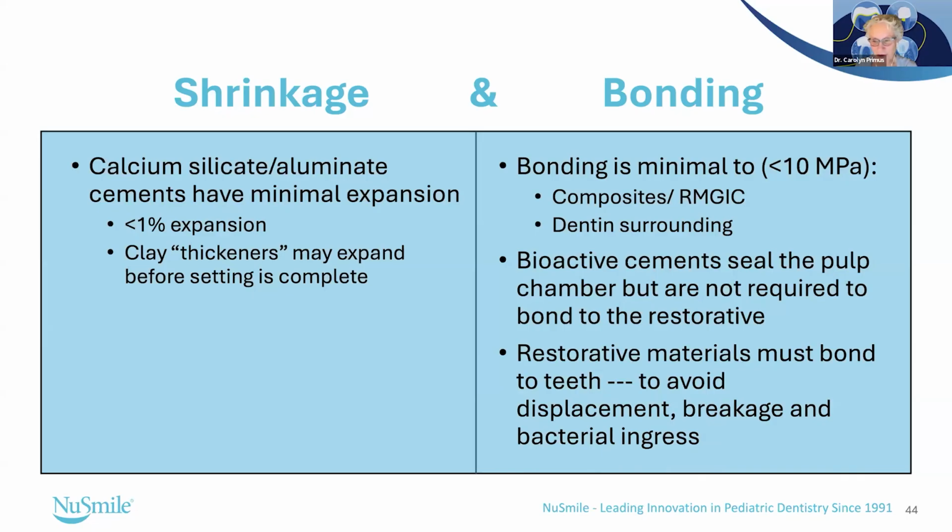You use the restorative over it, which must bond to the teeth because you want the restorative to stay in place, to not break, and to prevent bacterial ingress. So the lack of shrinkage is great. And bonding, I can't get excited about some of the data about that compared to restorative materials, which need to have a bonding strength of about 20 to 30 megapascals.